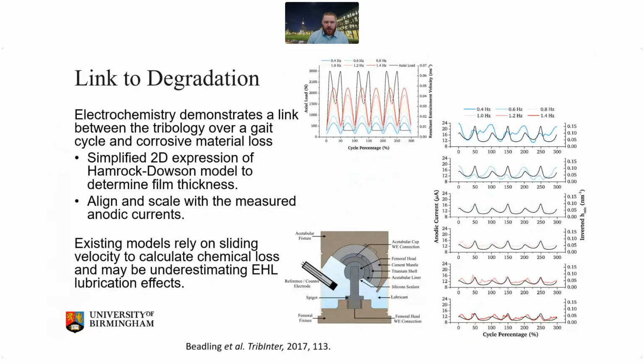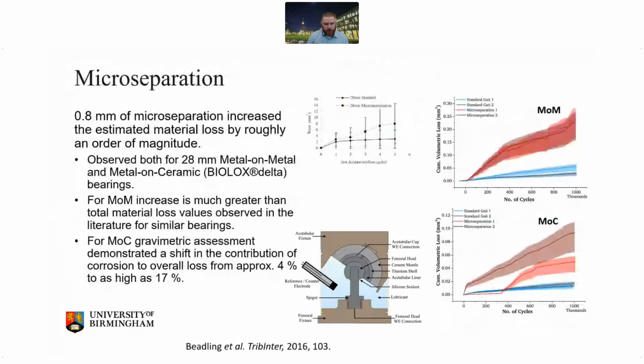But what we found is that actually the inverse was true, in that when you kind of trended to zero, or when you slowed down in terms of sliding speed, you actually compromised the fluid film more than anything else, and then that resulted in greater corrosion and peaks in corrosion current. So there was a bit of an upending of what we believed there. The other thing was microseparation.